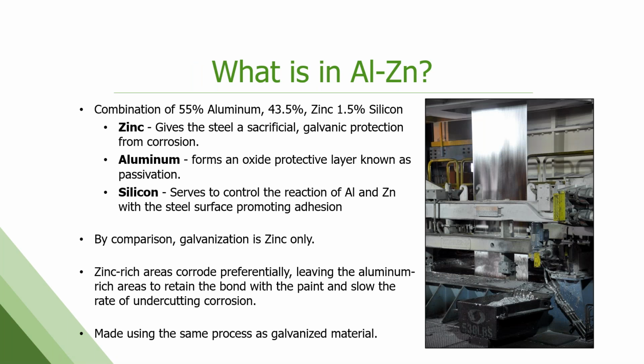So again, it's 55% by weight aluminum, 43.5% zinc, and then 1.5% silicon. The silicon is in there for reactive purposes and wetting out purposes in that molten bath that it goes through, not really doing anything in the final product. But zinc is going to give you a sacrificial or galvanic protection, right? It's going to sacrifice itself to protect the steel underneath, while aluminum forms kind of a protective barrier oxide, right? Passivation that becomes very inert and doesn't really corrode much further after that initial oxidation level forms. So when we talked earlier about sacrificial and protective barrier, that's where it's coming from, the zinc and the aluminum.